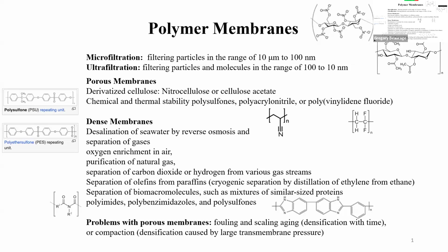So two things with the same delta will have a chi that's very low within the mix. So with chemical groups, you can just look at the groups in a polymer and see if they match up with the thing that you want to solubilize in it. So basically, that's generally how people do things.